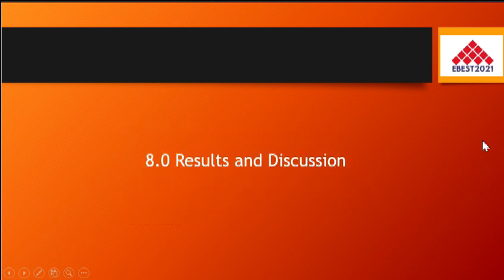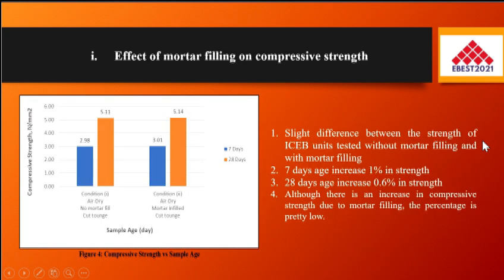Now let's see the results and discussion of this study. The first one is the effect of mortar filling on the compressive strength. As we can see from figure 4, there is only slight difference between the compressive strength of ICEB unit tested without mortar filling and with mortar filling. Although there is an increase in compressive strength due to mortar filling, the percentage is pretty low, where 1% increase at 7 days and 0.6% increase in strength at 28 days.